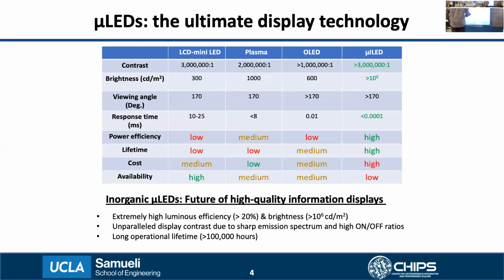If you see the slide, micro-LEDs are essentially the ultimate display technology. This table compares different display technologies that are commercially available versus micro-LEDs. What we typically observe is that micro-LEDs can provide far superior brightness compared to these other display technologies, with a brightness exceeding about 1 million candelas per square meter, which is 3 orders of magnitude better than the next best, which is the plasma display.